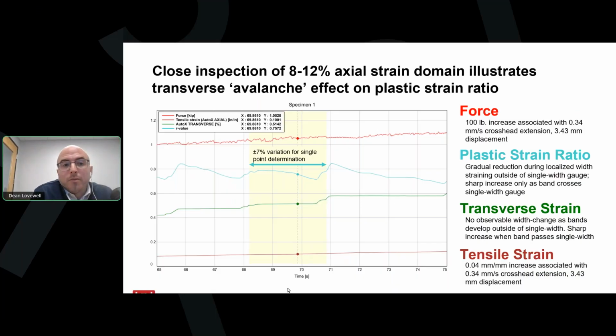So here what I've done is I've zoomed in on the region where R value is calculated. So the 65-second mark corresponds to 8% axial strain, and the 75-second mark corresponds to roughly 12%. So we see the direct contribution of the stepped green transverse strain plot and how it affects the teal calculated R value or plastic strain ratio. So looking at a single point, the 10% axial strain that I've highlighted here in yellow, we see that R value increases with an observed increase in transverse width because the metal has shown its ability to stretch in plane.